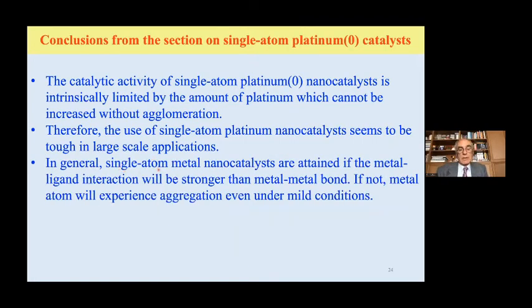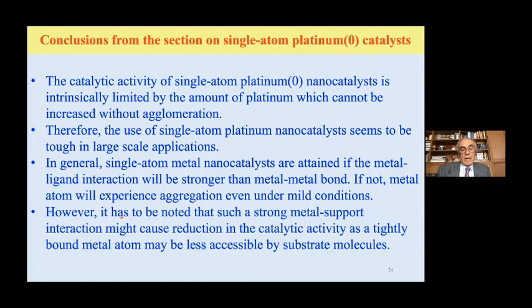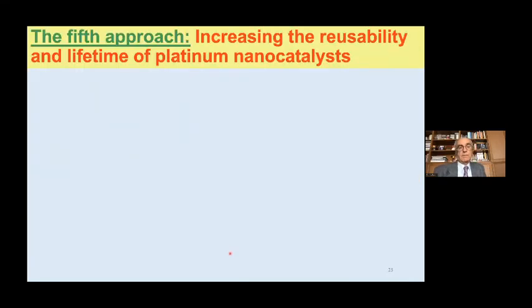In general, single atom metal nanocatalysts are attained if the metal-ligand interaction is stronger than the metal-metal bond. Otherwise, we should not be able to get the single atom. Metal experiences aggregation, even under mild conditions. We have to remember that such a strong metal-support interaction might cause a reduction in the catalytic activity as well, because a tightly bound metal atom may be less accessible by substrate molecules.